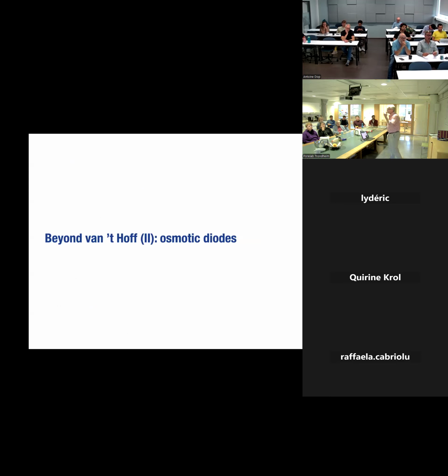What is funny is that if you take a polymer, but a polymer which is very neutral to the surface, then the effect is reversed. Meaning you see here, velocity, it goes in this direction. So here it's like this. And this is because the polymer is slightly depleted from the surface because of its finite size. So it's a steric repulsion. So then the mobility scales like minus the radius of gyration squared of the polymer. And so you have a sign inversion. So meaning indeed you can have both signs. And this can be completely explained by the basics. Okay, so it's just the first illustration of going beyond van 't Hoff, let's say.